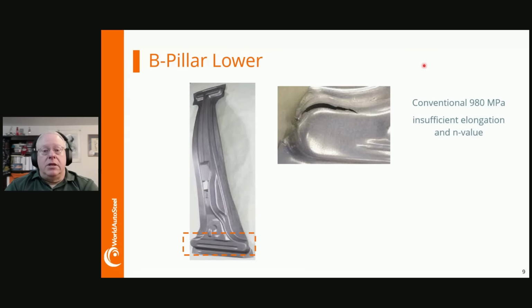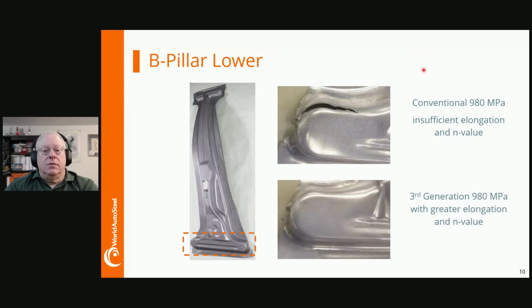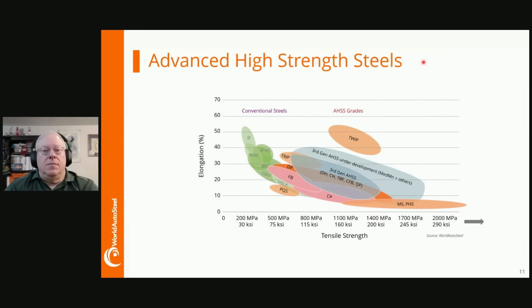From a formability perspective, the deep draws and aggressive designs put these stampings at risk of splits due to insufficient elongation and n-value. However, after changing the grade to a third-generation steel of the same strength, but with greater elongation and n-value, no issues were found when stamping this deep-drawn part design.